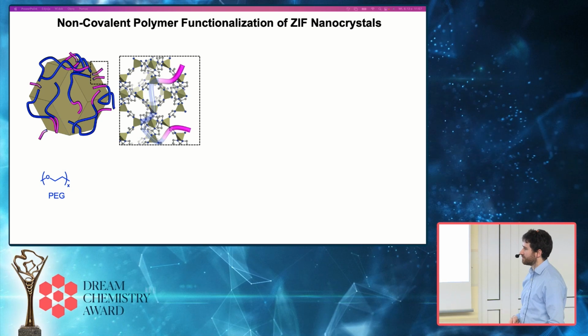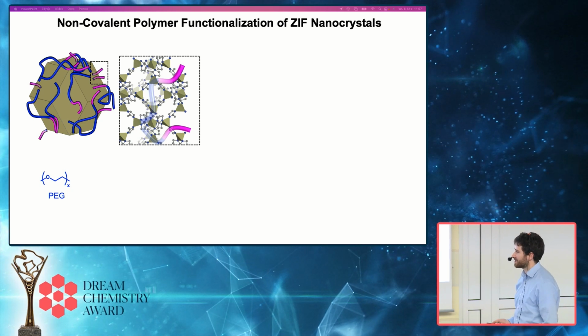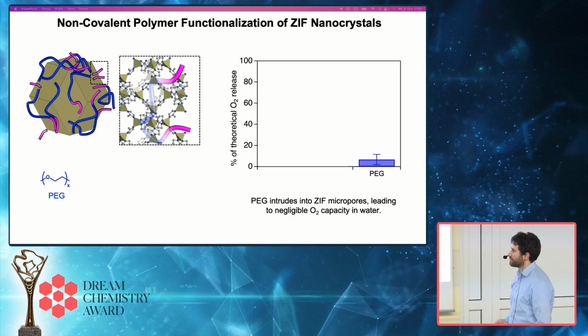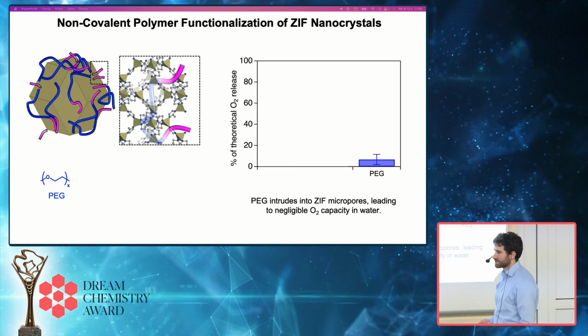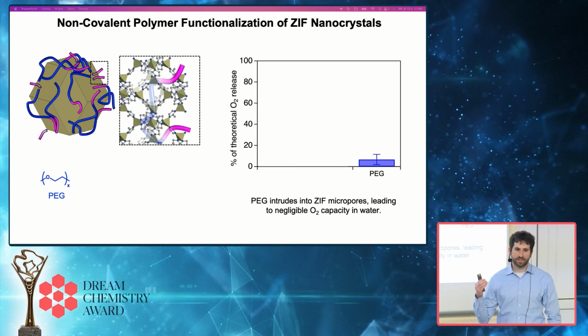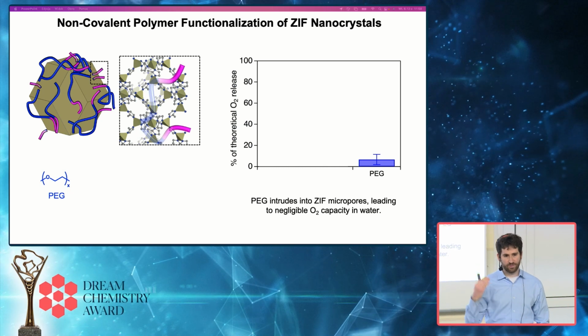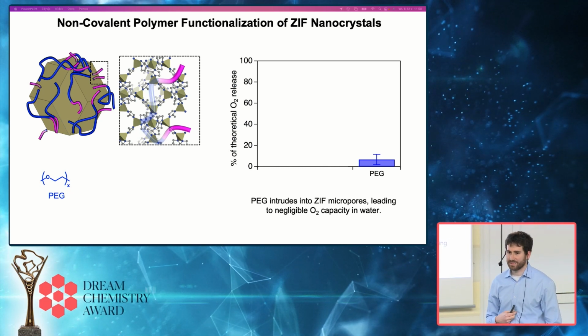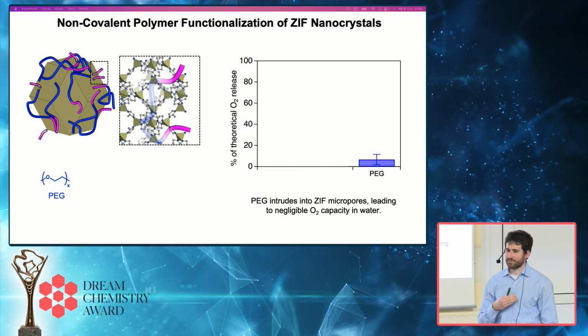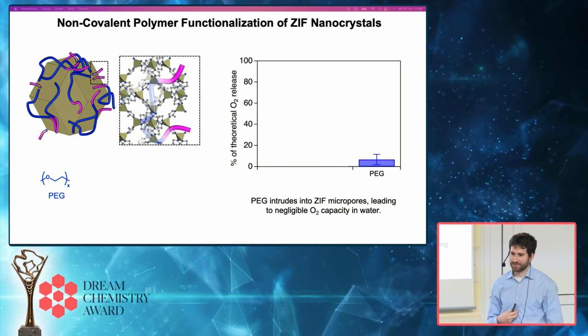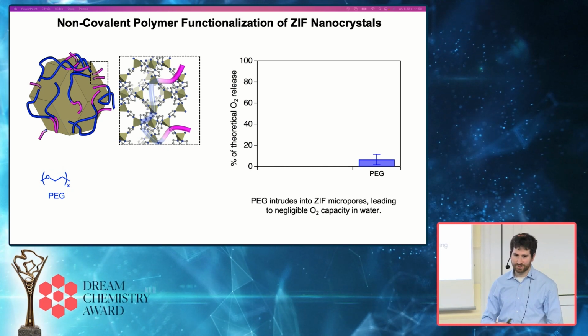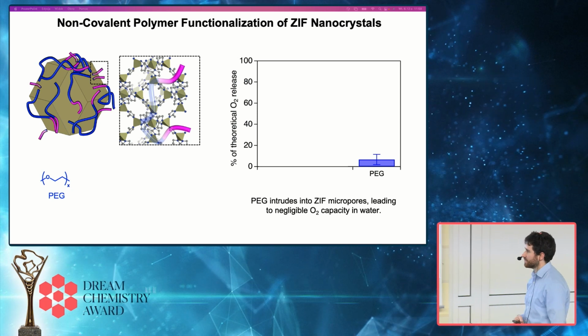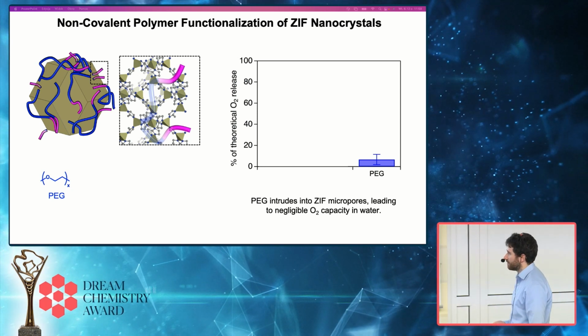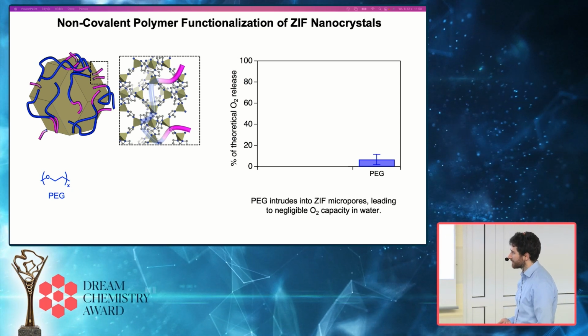PEG generally cuts down on protein absorption and tends to make things more biocompatible. The problem with PEG for these MOF nanoparticles is that PEG is quite small, and it's thermodynamically favorable for PEG to go inside the pores of our material. And so PEG rapidly intrudes into the material's pores. You lose all your porosity, you lose all your oxygen carrying capacity, and so it's not an effective strategy for making these materials dispersible in water.